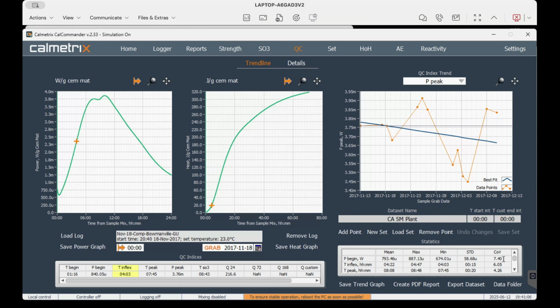But for each of those, you have those different parameters and those different statistical values. And you remember, for example, that I said that in ASTM C563, they tell you that the time between the main peak and the sulfate depletion peak is a very good indicator of consistency.